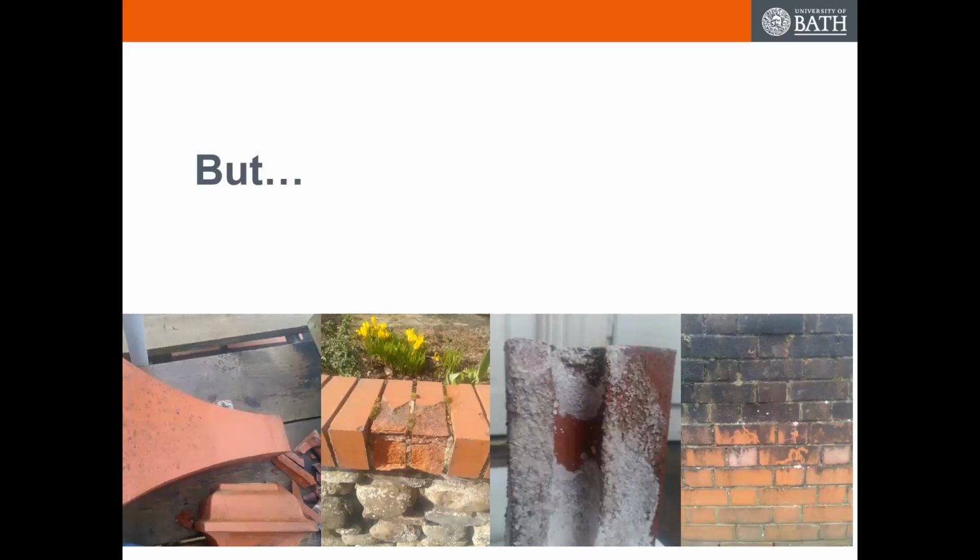But that's another garden wall, and it has two different types of bricks. That classic one where you've got that low wall that everyone trips over, so they add another four courses on top, so then you can lean on it instead. The bricks have slightly different roughness and slightly different porosity. The course on top is absolutely covered in biofilm all the way along the wall. The courses below aren't, and have a few traces of biofilm basically hanging down from the bricks above them.